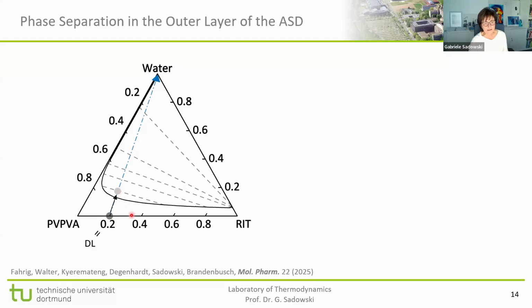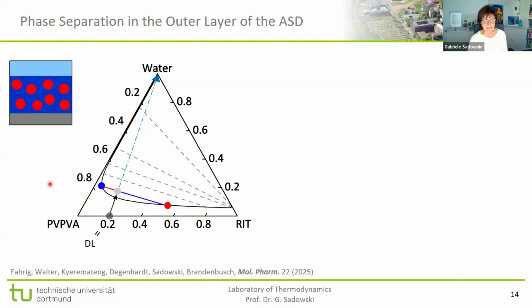And that means if we are in a miscibility gap, we get two phases, a ritonavir-rich phase and a polymer-rich phase. And then we have the lever rule, and that means we have much less of the ritonavir-rich phase compared to much more of the polymer-rich phase. And this looks like this. So what you see here is a tablet. This is a dry system. This corresponds to this point. Here we have water from the dissolution medium. This enters the tablet, brings us up here, and then we get two phases. And we have a lot of the polymer phase and a little bit of the ritonavir-rich phase. So we can imagine this like droplets of ritonavir-rich phase in the continuous phase. This is what we would get for small drug loads.